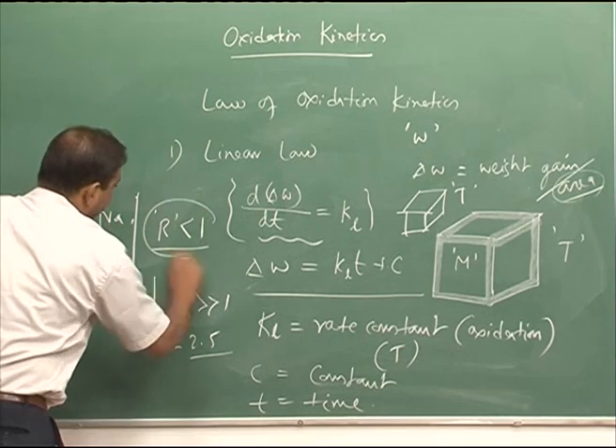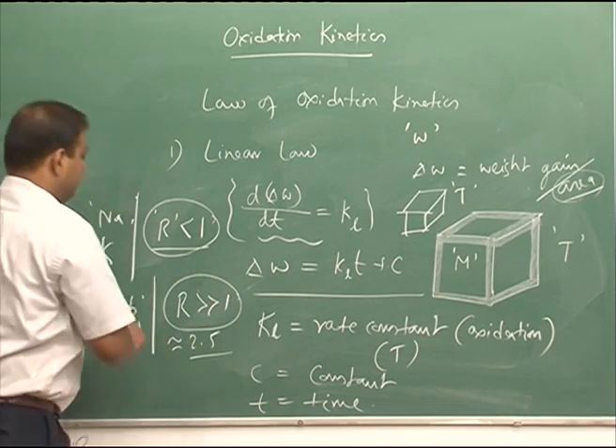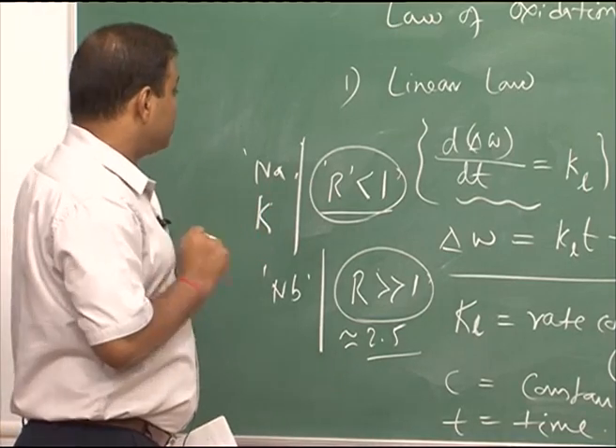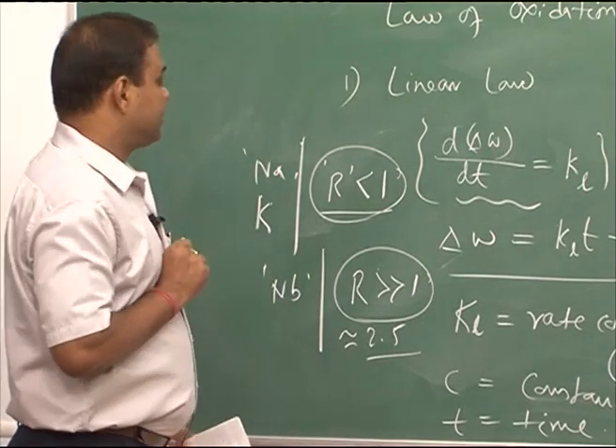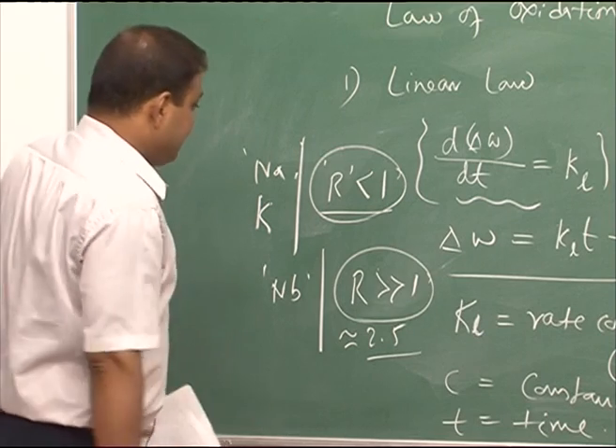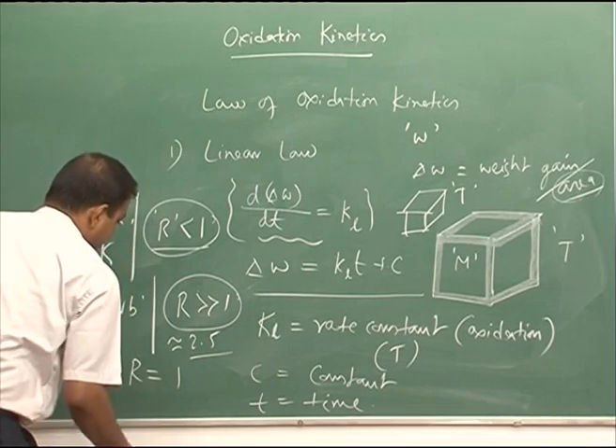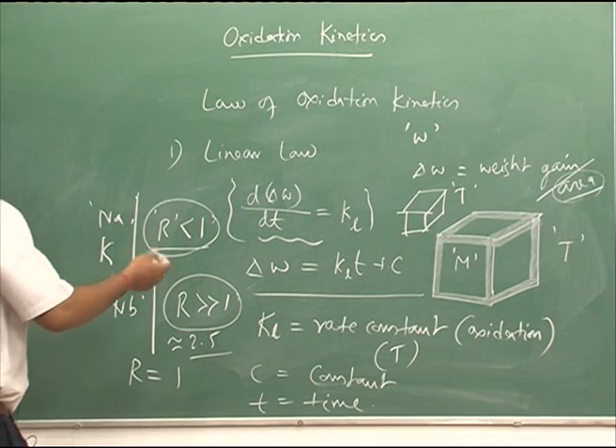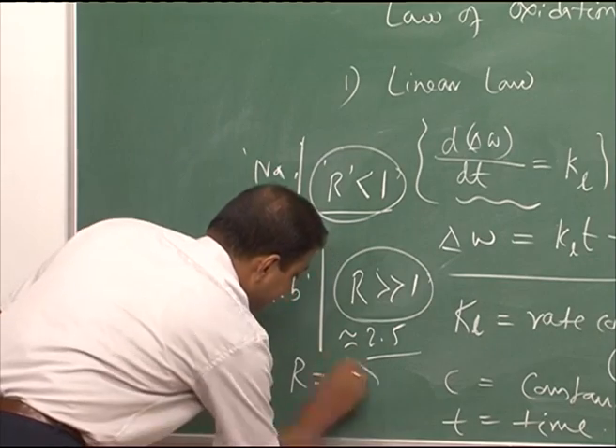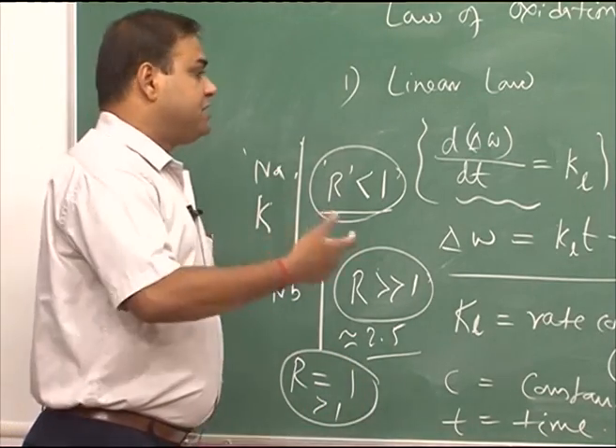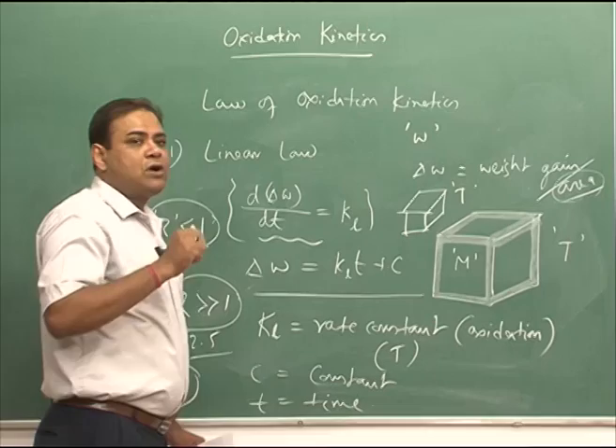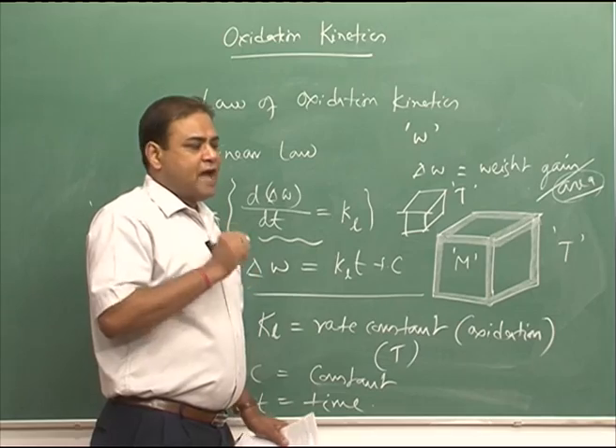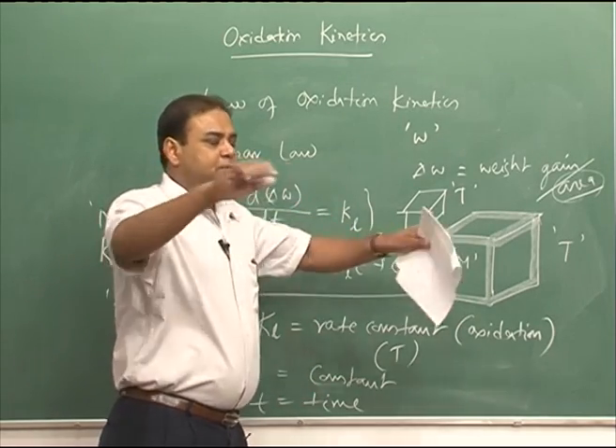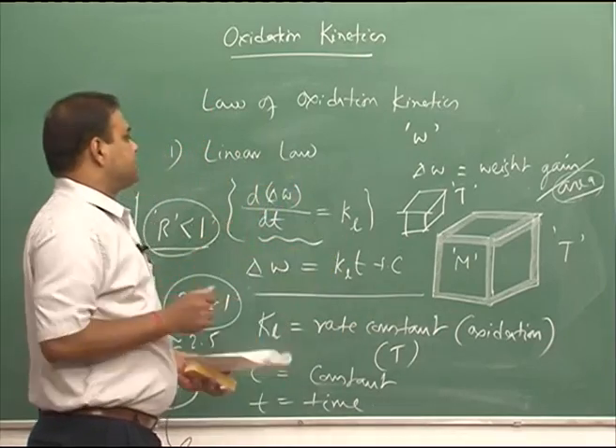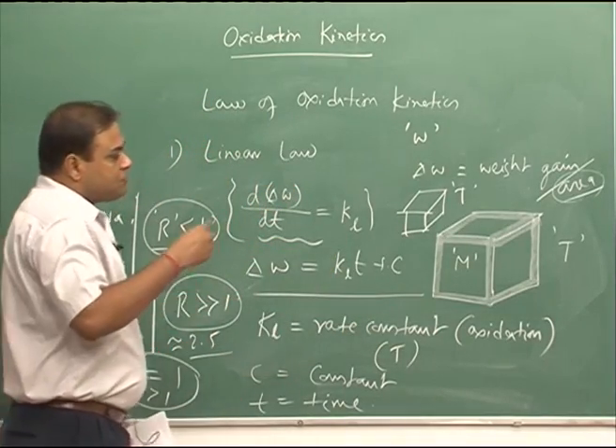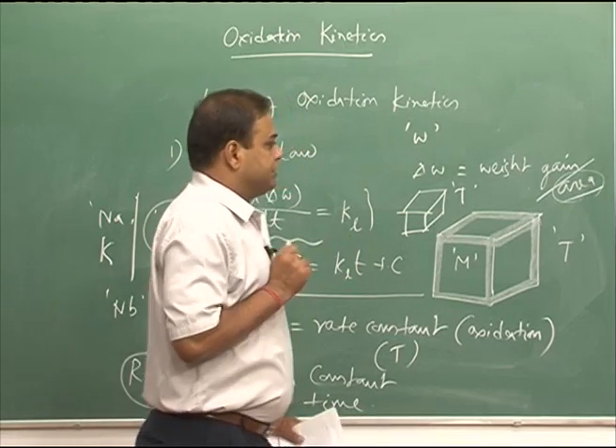And now we see that for R less than 1 and R much higher than 1, we have the problem of not having good protection from the oxide formation. But if R is close to 1 or a little higher than 1, it should not be less than 1, then we would see that the oxidation resistance would be relatively good. For example, aluminum, where the R value is around 1.28, the metal oxide would be protective throughout the metal surface and form uniformly, and that is why aluminum gives you very good oxidation resistance in normal atmospheric conditions.